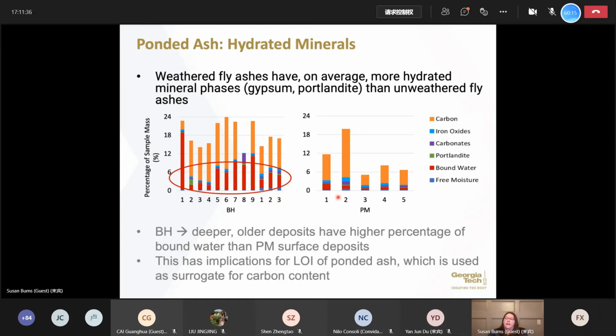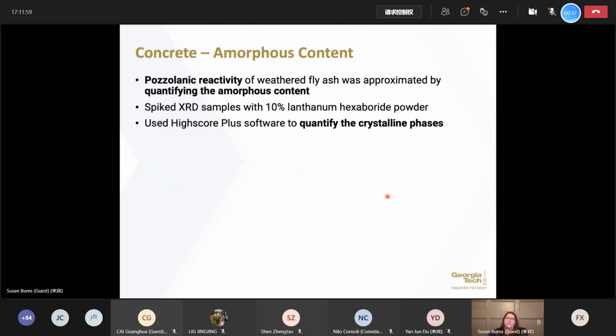When we compare that to relatively younger deposits that we see here on the right-hand side, right? So when we think about LOI of older weathered fly ash, it's a little bit misleading if we think of that as a surrogate for carbon content. So we have to be careful to make sure that we're not mixing hydrated mineral phases as a substitute for carbon.